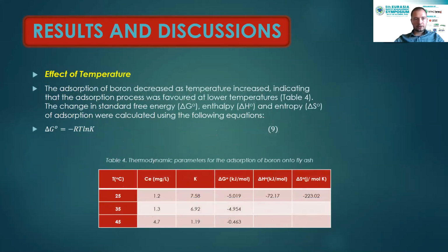Effect of temperature. The adsorption of boron decreased as temperature increased, indicating that the adsorption process was favored at lower temperatures. The change in standard free energy, enthalpy, and entropy of the adsorption were calculated using the following equations.